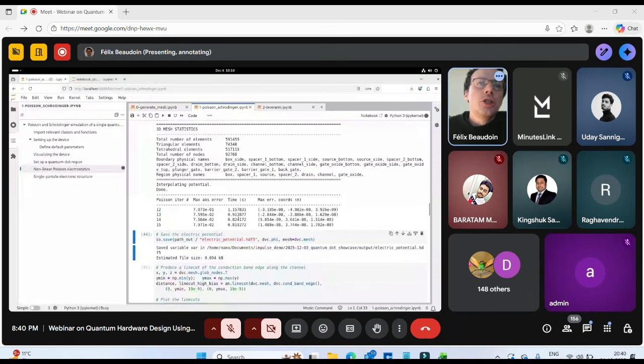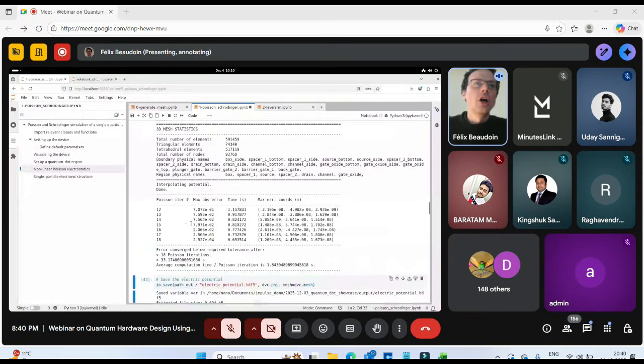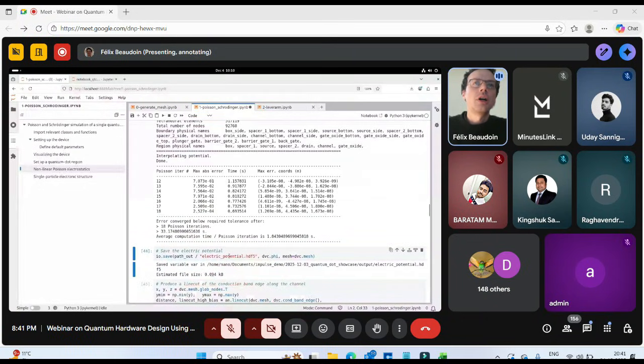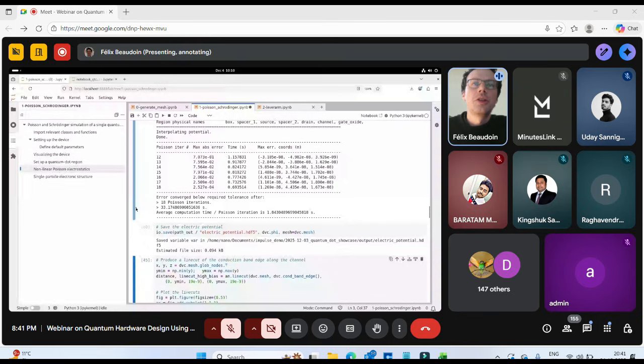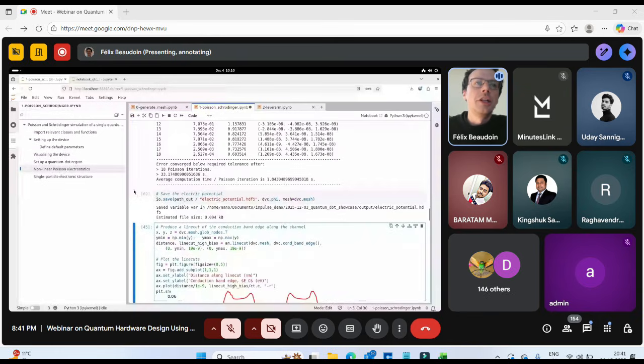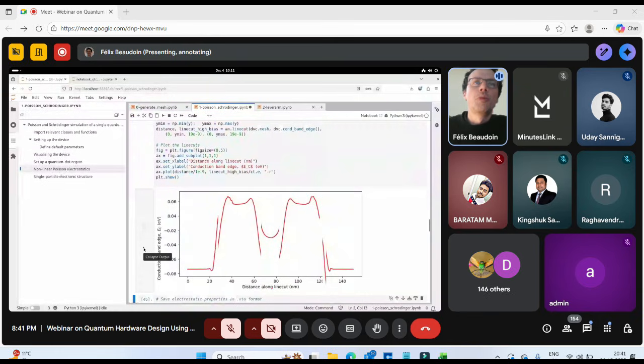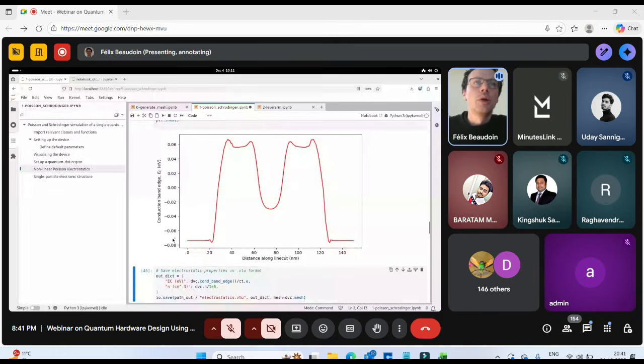So we can save the electric potential for visualization. We can also do a line cut of the conduction band edge along the channel. And here we can see the line cut. Because we have very strong doping in the source and drain, the conduction band edge goes well below the Fermi level, which is at 0 on this plot. We have beautiful barriers associated with the barrier gates, and we have a well associated with a plunger gate. And now we have a quantum well. The question is, can we really get bound states in that quantum well? And to answer that question, we need to solve Schrodinger's equation in the dot region.